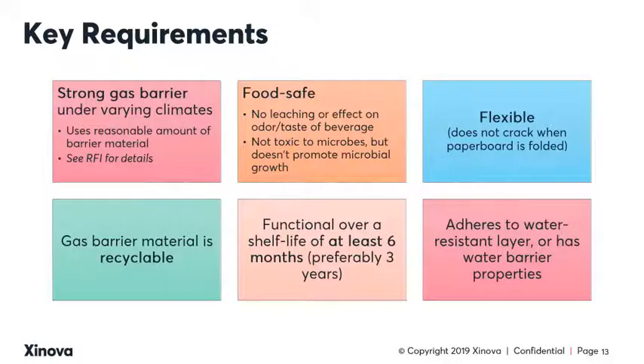Again, the material should be flexible, so it doesn't crack when the paperboard is folded. The barrier material should be recyclable, and this is where it would differ from the current standard of aluminum. Since this is being used in aseptic packaging, it should be functional over a shelf life of at least 6 months, preferably 3 years. And finally, it should adhere to the water-resistant layer, or if it has water barrier properties, then we are eliminating the need for a water-resistant layer, which is actually an added advantage.